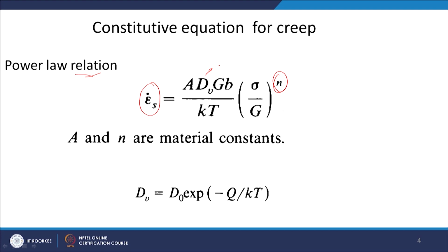D is your diffusion coefficient, okay, which is basically D naught exponential minus Q by kT. Q is your activation energy for diffusion, okay. G is your shear modulus, okay. b is of course your Burgers vector, okay. k is your Boltzmann constant, and T is of course temperature in Kelvin, okay, and the stress is actually, as you can see, normalized with shear modulus here, okay.